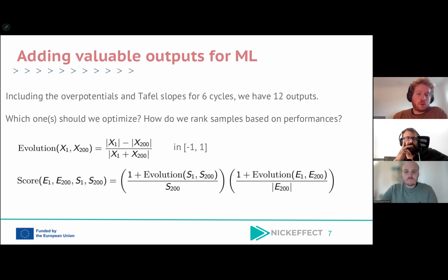That includes the potential at the first and last cycle, the Tafel slope at the first and last cycle, and also their evolution. So we basically want a positive evolution. We want the sample to evolve positively. And we also want the Tafel slope and the potential to be as low as possible in absolute value, so as close to zero as possible. And so we define this score so that the larger the score, the better the film in the end. Using this score, we can actually rank the different films that they were depositing.